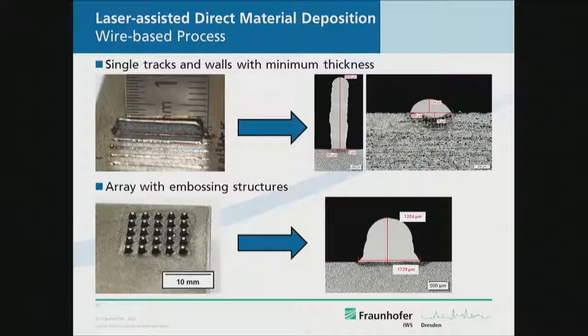Now, you might ask yourself, is it possible with wire as well? This gives you some examples of wire-based, small-size features. Again, I'm unfortunately not allowed to show you real components here. Just a few examples. As you see, wire is not as precise as powder, at least not up to now and today. But still, we can make nice features, also small-scale features. This has a couple of millimeters in height, 400 microns in diameter. Wall thickness is not as precise as we can guarantee for the powder-based process, but not that bad. All right.